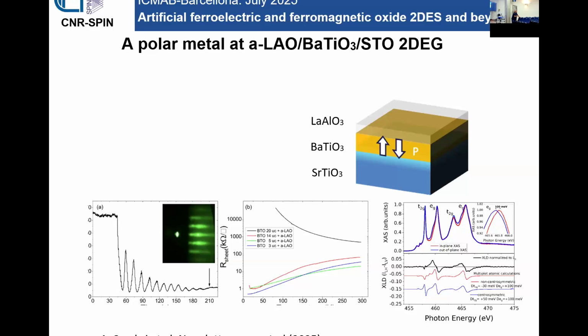There is some dipole component, which you can call ferroelectric. We call it ferroelectric-like, let's say. But at least it has a non-volatile effect on the properties, on the ionization and transport properties. In that case, you should have a metal which is ferroelectric. Probably a metal can be ferroelectric if the screening is not good enough. In some sense, yes. But another possibility is a disordered phase, or a homogeneous ferroelectric-like material. I'm not completely sure.